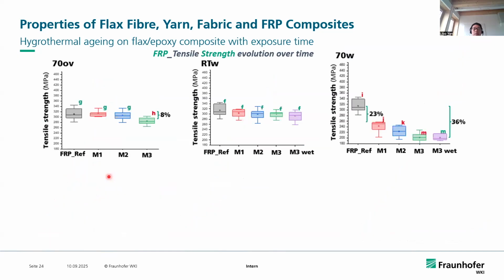Those results highlight that moisture is the main enemy of flax epoxy composites. When the temperature is low, of course below the glass transition temperature of the epoxy, it's tolerable. But heat plus water accelerates the degradation of the fiber reinforced polymer composites significantly. Let's have a closer look at the hygrothermal aging effect on the flax epoxy composites over different exposure times.